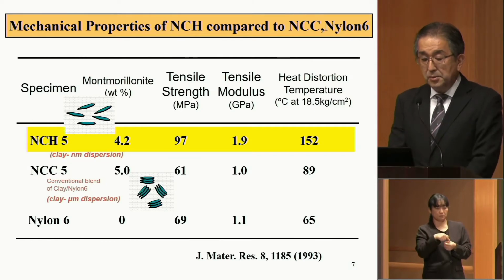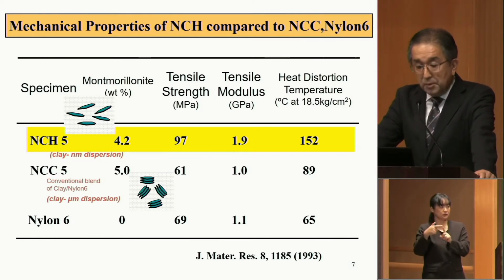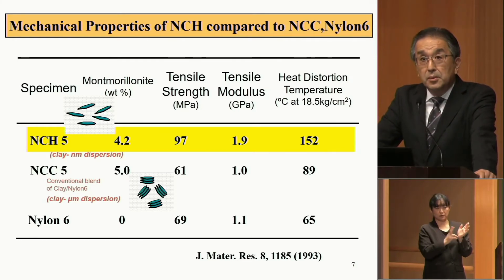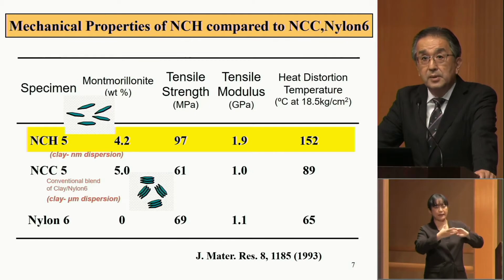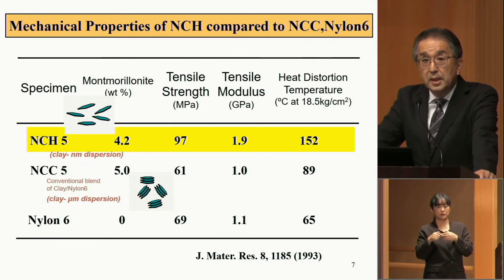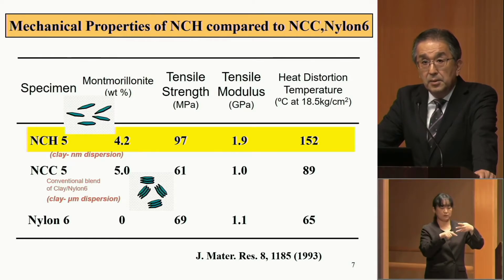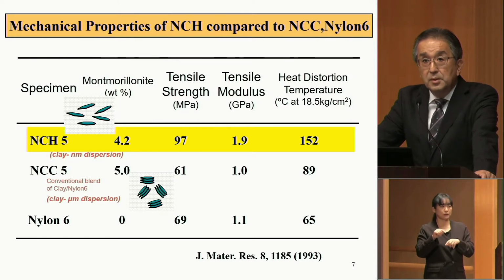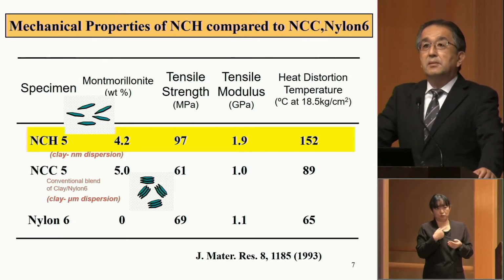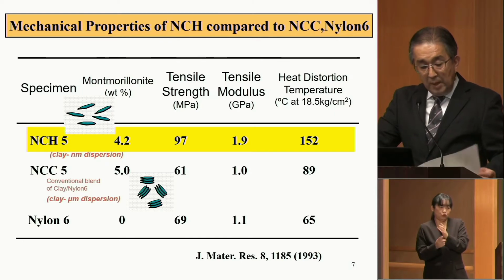We named this nylon clay hybrid, or NCH. NCH has high tensile strength, tensile modulus, and heat distortion temperature, which is a critical factor for vehicles. Just by adding 4.2% of natural clay, compared with pure nylon 6 at the bottom, tensile strength increases by 1.5 times, tensile modulus by 2 times, and heat distortion temperature by 90 degrees. The amount of added inorganic ingredient is very little, so the material is light, strong, and heat resistant.